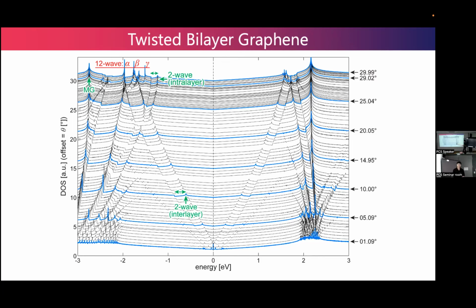Here I plot the density of states of twisted bilayer graphene for various rotation angles, from 1 degree to 30 degrees. This is the Dirac point, and the conduction band and valence band sides. Some features are universal to every angle. For example, this is the band opening by two-wave interlayer interaction. That's the typical interaction you see in the K-space Dirac cone interaction in twisted bilayer graphene, and it's common in every angle.